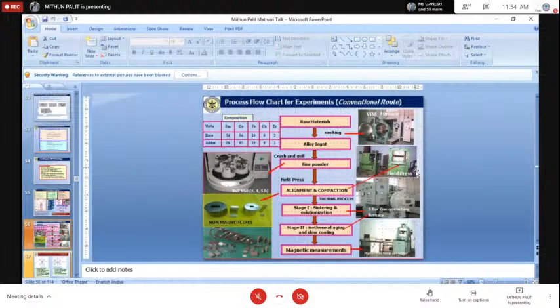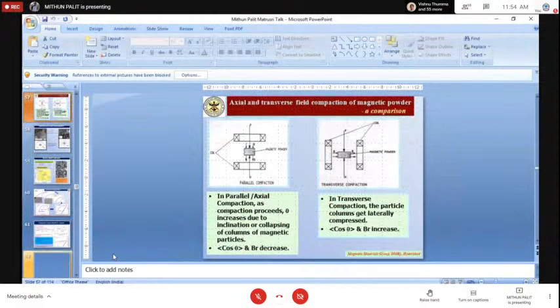And subsequently, in this case we also apply pressure to make a handleable green compact strength, and apart from that we apply the strong magnetic field to orient the powder. So this oriented green compact is subsequently sintered, and then we can fabricate different types of components as shown in this slide. Well, I was talking about the compaction. There are two types of compaction we generally adopt.